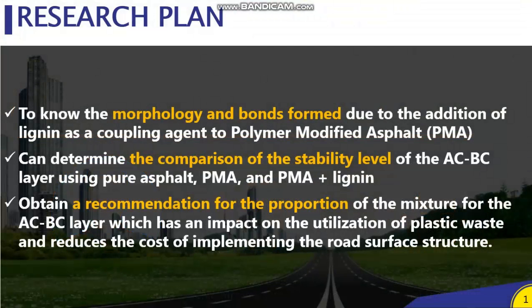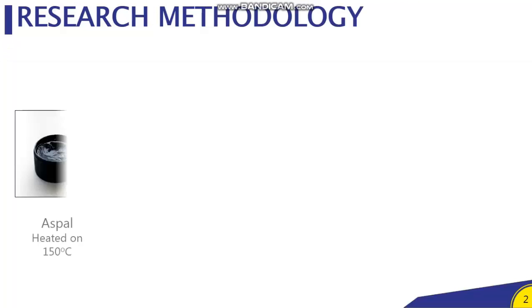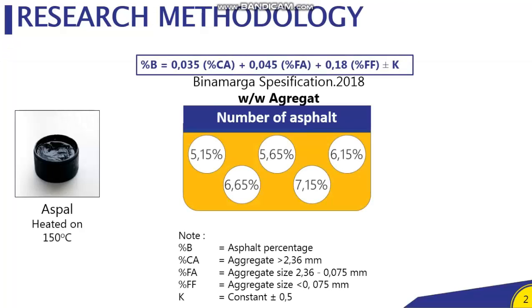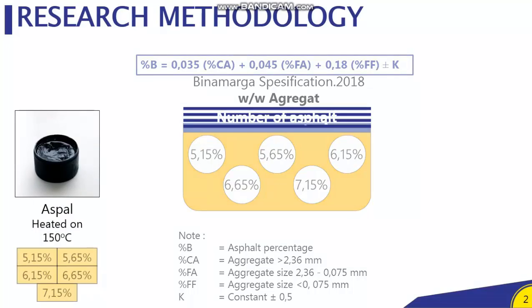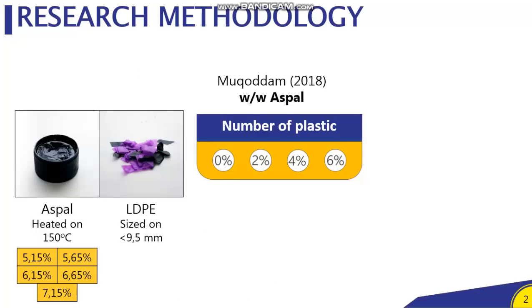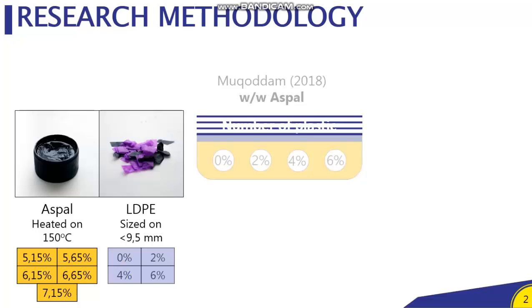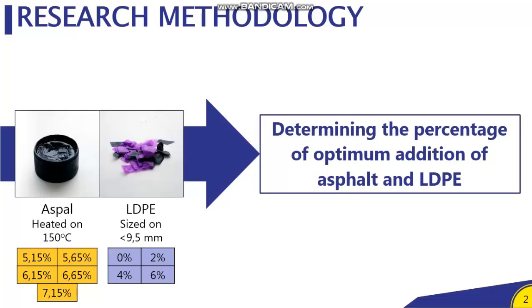There are three main topics in this research. Initially, we determined the percentage of asphalt content following the Bina Marga specification. From this calculation, we determined 5 numbers of asphalt content. Then we determined the percentage of polymer from previous research by Muqoddam 2018, using 4 numbers of plastic content. The result of this part is the optimum proportion of asphalt and LDPE content.